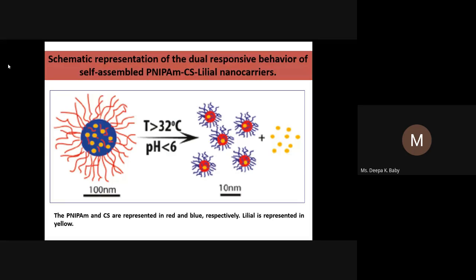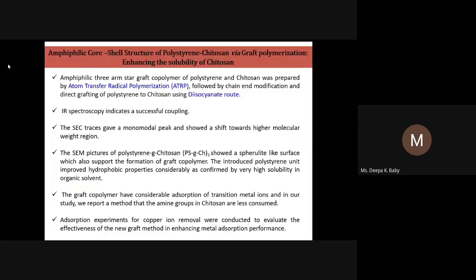This is the micelle. At lower temperature, the red lines are NIPAM, and inside you have chitosan, and the yellow region is the Lilial drug. So Lilial is trapped inside the micelle and it is in a safer place, at a temperature of 25 degrees Celsius. When it is taken to a higher temperature, that is above 25 degrees Celsius, the reverse process takes place. That means now NIPAM is hydrophobic. It will be inside the micelle and chitosan will be outside. So since chitosan is outside, Lilial is there with the chitosan and release of drug takes place.